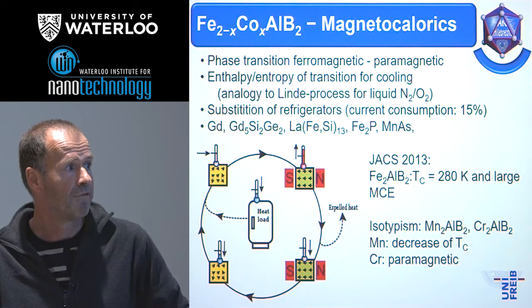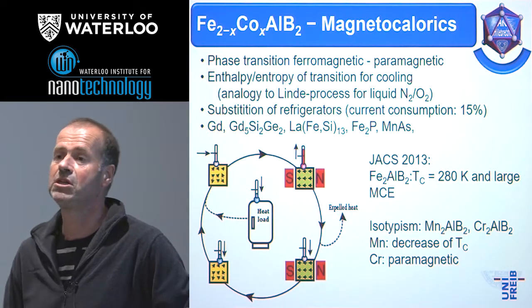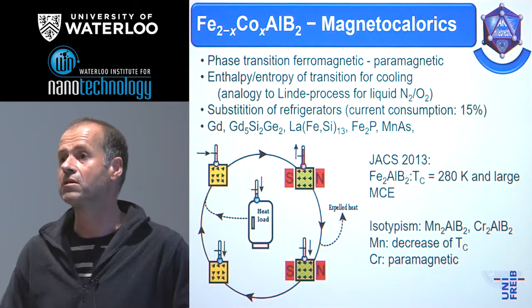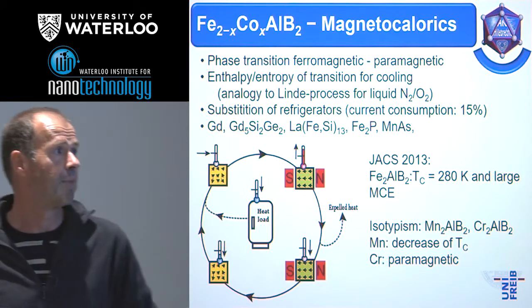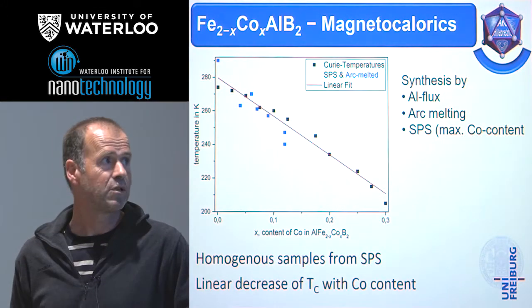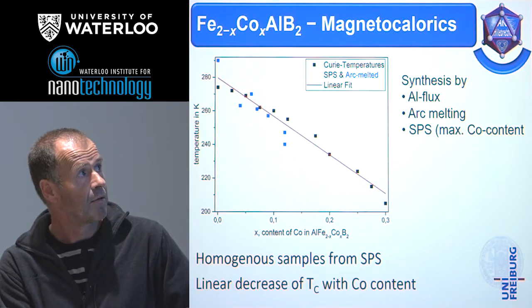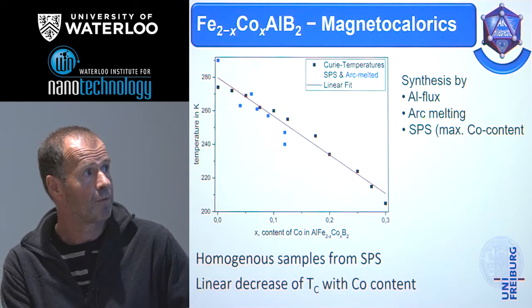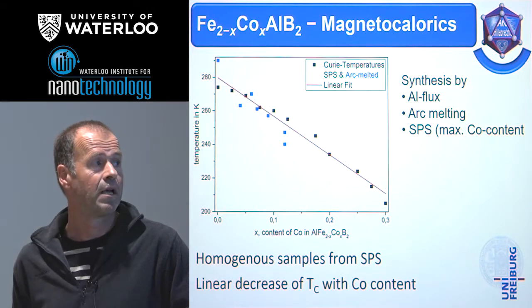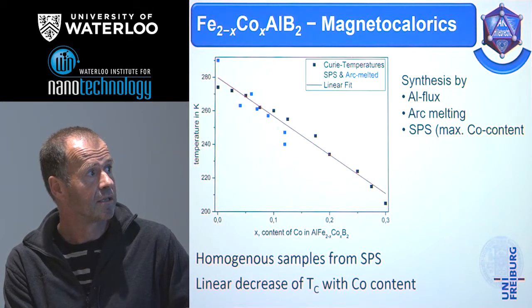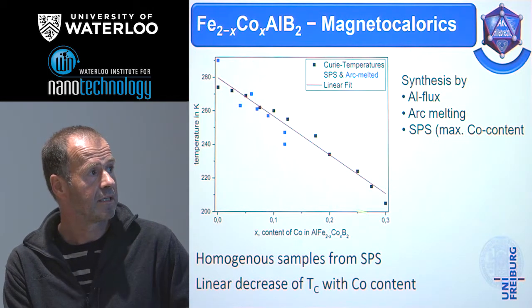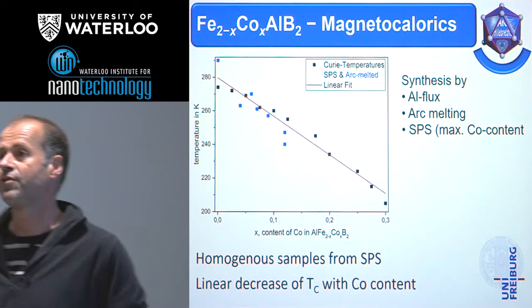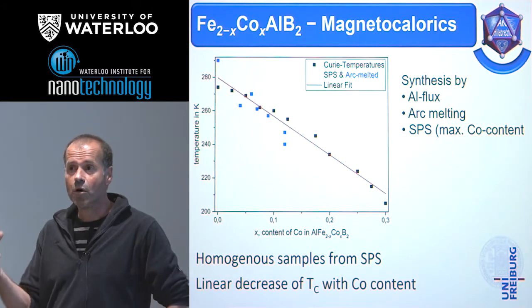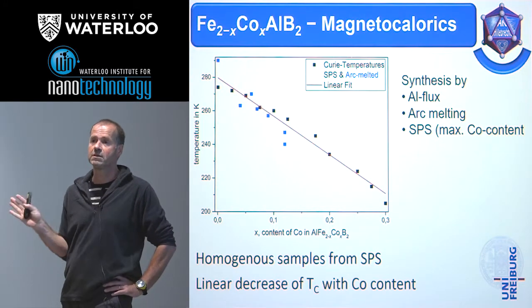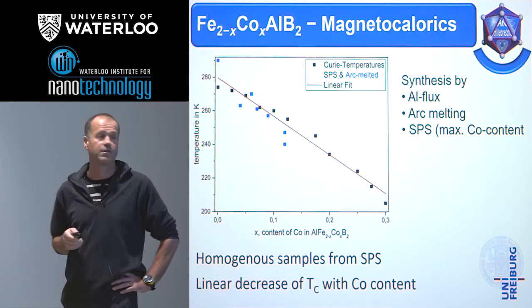And this was not the case for manganese. It was possible to do the substitution, but the transition was very broad and so no longer useful for magnetocaloric applications. And my master student was able to develop a process first by arc melting, later on by this pulse plasma synthesis, and she was able to substitute a part of the iron by cobalt, and we could show that we get a linear decrease of the Curie temperature with increasing cobalt content. And this is exactly the field where we can assume low temperature cooling applications. That means around 200 K. That's the lower limit which is sensible for technical application.